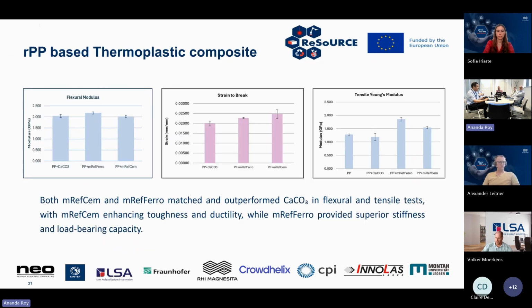So it enhances those systems within the composites of the polypropylene. It is quite substantial. Again, looking into the mechanical properties of this thermoplastic polypropylene, firstly, the flexural modulus is not affected very highly. So basically, the stiffness remains very similar. But then you can see that ductility within the mRefCem is increased within the strain to break, as you can see with this testing.